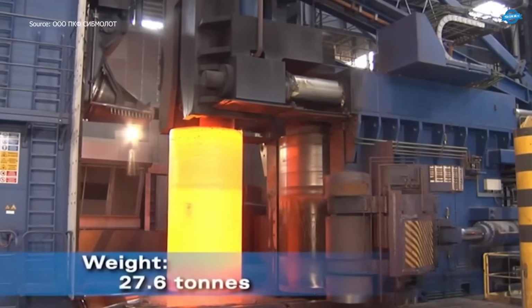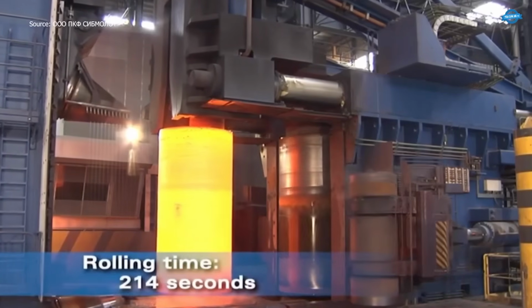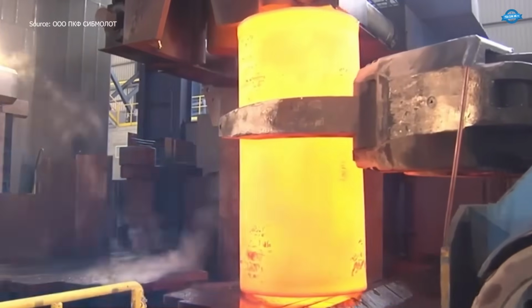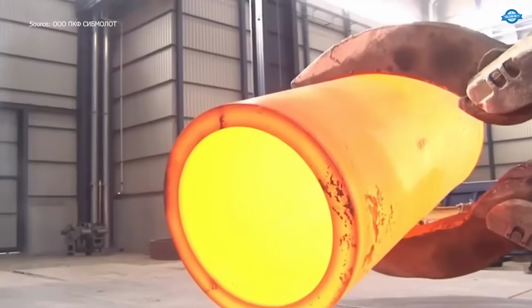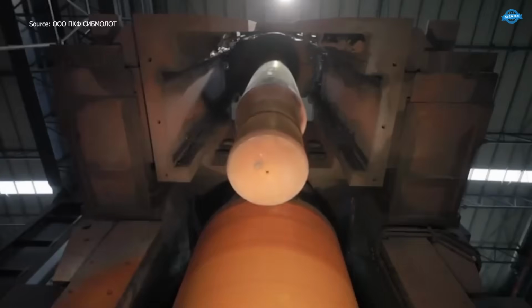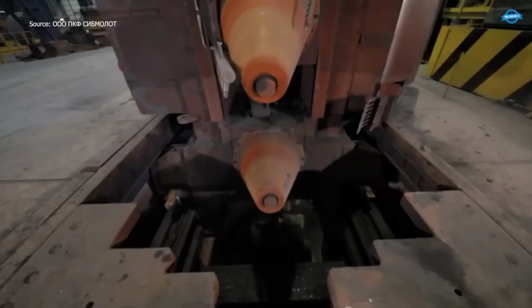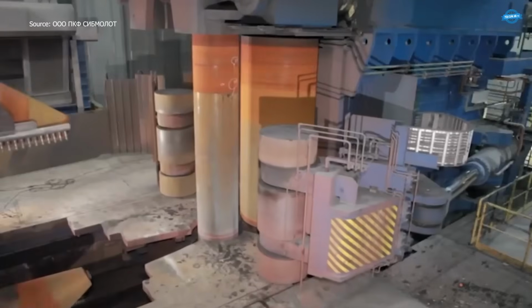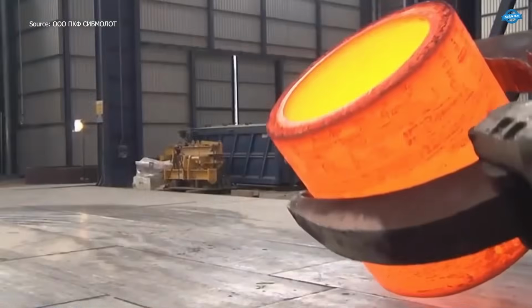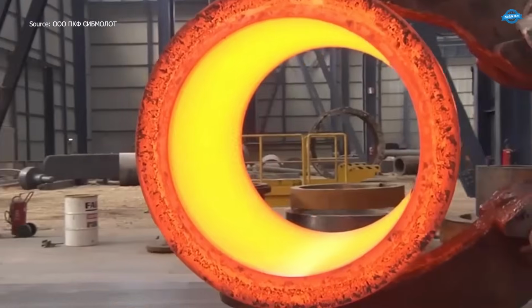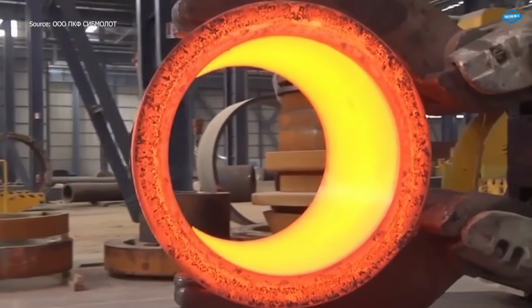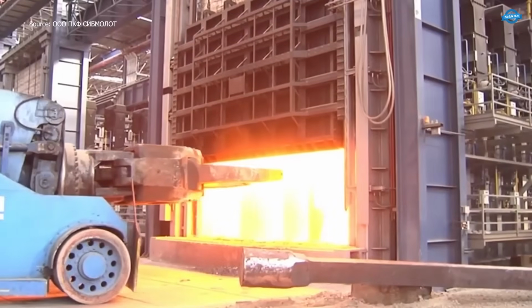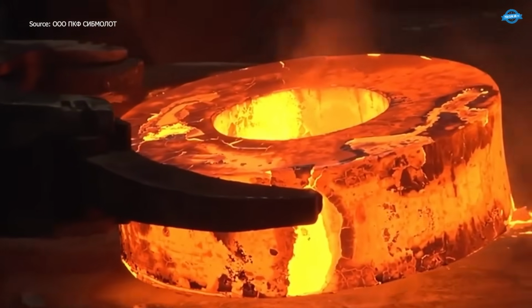A larger blank, measuring 1,584 millimeters inner diameter and 1,288 millimeters height, undergoes similar operations. Over 460 seconds, the machine produces a rolled ring weighing 89.3 tons with a wall thickness of 566 millimeters. The rolling action combines radial and axial movements, ensuring uniformity across the enormous surface.